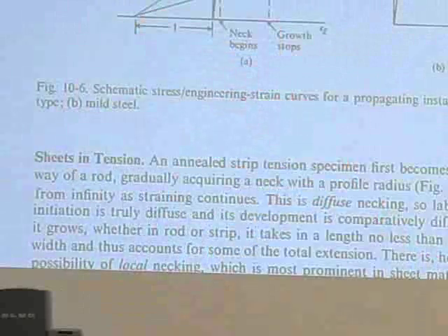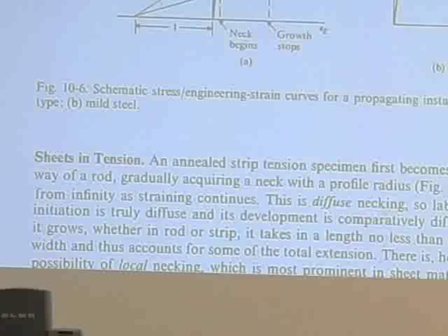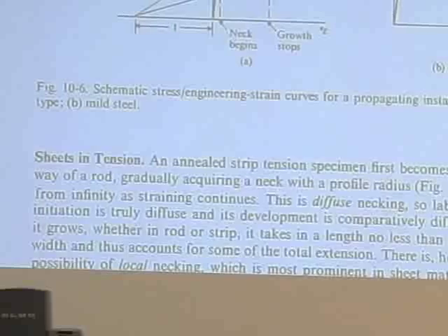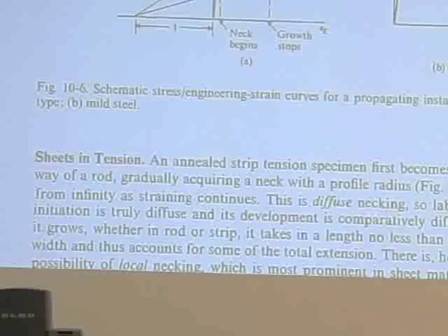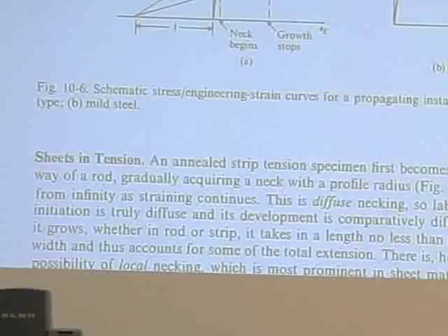Well, you get the same thing in the steels. You'll get these bands that they used to call stretcher strains, because you're doing a deep drawing operation and you'll get this band going right across your material. If you were to draw everything far enough, you could stretch them all the way out and get rid of the bands, but in fact that's not the way a hood or a fender on a car works. You would leave these in and it'd be a piece of junk. You'd have to throw it away, because when you painted it, all you'd have is these ugly looking stretcher strains in your sheet metal where it had locally necked down.